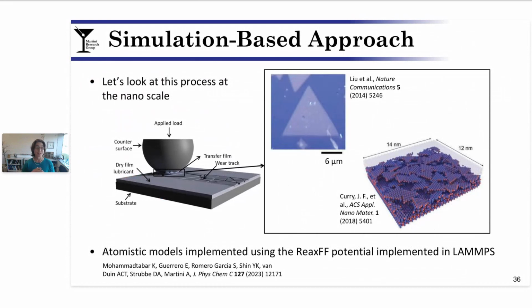The other advantage of this idea of the flakes or the debris is that we can zoom in a little bit closer and focus on nanoscale mechanisms. So we take our tribological system and we zoom in just to the debris, just to the contact. MoS2 has been shown to be a triangular shape, which is prototypical or expected in equilibrium conditions, as shown in the microscope image here. And this idea has been leveraged in previous simulation studies to model the MoS2 at the atomistic scale. We followed a similar approach in our work, and for those who care, we developed atomistic models using the ReaxFF potential as implemented in LAMMPS.